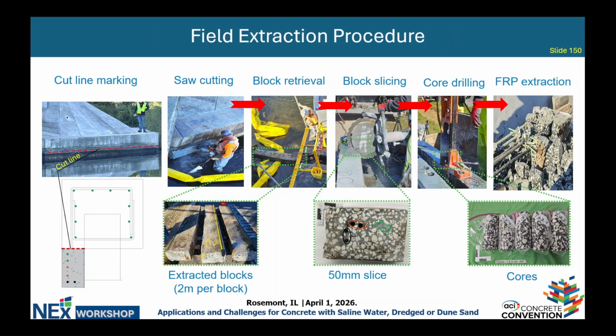In this slide, we show how we transfer from field exposure scale to laboratory testing scale, starting with marking the lines, then marking the cutting lines, and then performing saw cutting horizontally and vertically, and then retrieving the blocks. After that, we extracted our two materials. The first material is seawater concrete. We sliced the blocks, those are the extracted blocks. We sliced them here and took the extracted cores, and then we exposed the FRP reinforcement.